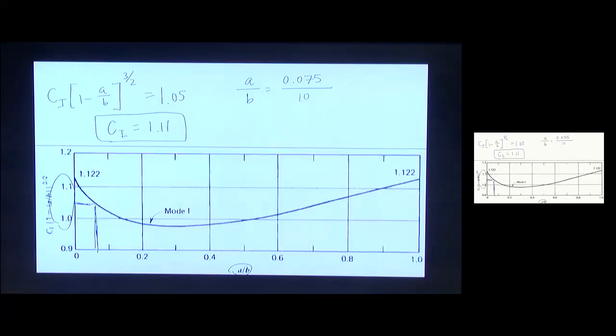And they point out that if the crack grows really, really big, so we don't know how big it's going to grow to be critical. That's what we're kind of checking right now. But let's say that it grows up to like 0.3 inches. So it's more than 3 times that length. What is the C1 in that case? It is 1.13. So the change is only in the hundredths place. So we're just going to use the first one and move forward from there.